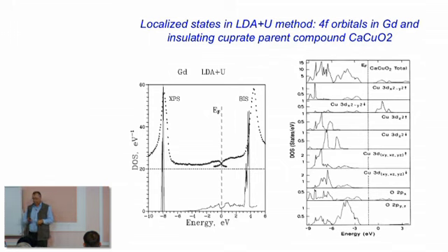Now examples, applications. Here we have gadolinium. That's exactly what I said: if we would calculate gadolinium with 7 electrons in the F band, that could contain 14 electrons, it will be a half-filled F band. Then we will have it immediately on the Fermi. So this very narrow band would be immediately on the Fermi and partially filled, which is completely wrong. For rare earth metals, there is nothing on the Fermi except SPD. F-electrons are not on the Fermi at all.